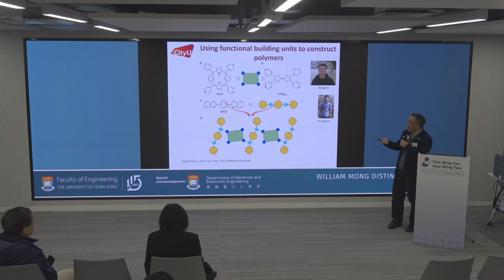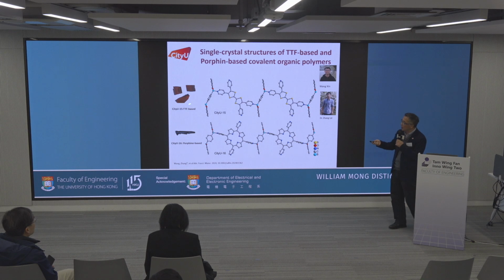Actually, when we controlled our experimental conditions, we found that whether it was the tetrapyridine porphyrin or the TTF, they only use two pyridines to coordinate with the boron, and leave the other two pyridines dangling. You can look here. We get a very nice crystal as shown here, and then we solved the crystal structures. You can see two pyridines dangling, in both the TTF system and the porphyrin system. And then these two pyridines connect together and form the linear structure as shown here.